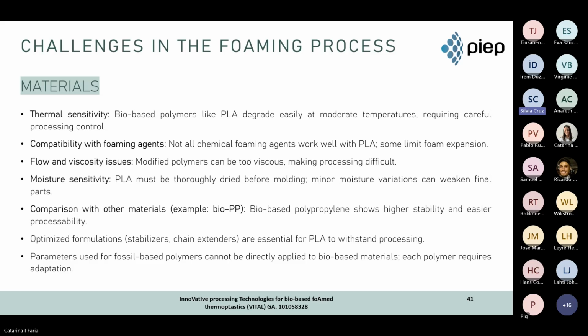Foam structure depends on gas solubility in the polymer. Some bio-based polymers have low solubility, so this could lead to poor cell nucleation or large cell size. So it required some nucleation agents, gas dose optimization, and precise injection profile control.